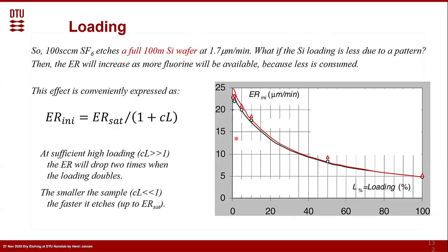But now we talked about it. What's the etch rate at 100 sccm? Let's say for the best and nicest performance it is roughly, for a full 100 millimeter wafer, 1.7 micrometers per minute. Now we put in a wafer, but the wafer is not 100 millimeter bare silicon like we calculated before. That means that the silicon loading is less due to the pattern.